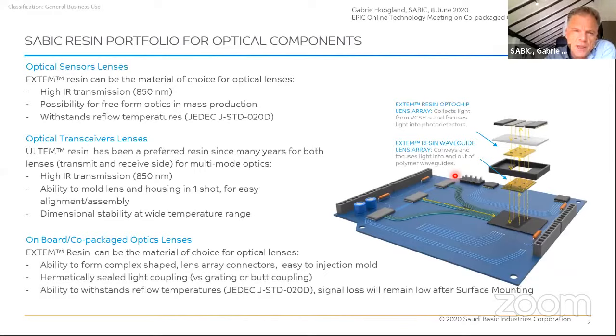molding machines, they can easily produce tens of millions of lenses in just a few months. The second example on this page is well known to you. These are the lenses used in a pluggable optical transceiver, which I guess everyone knows are mostly made from Ultem resin. And the reason why they use Ultem here, both on the TOSA and the ROSA side, is really the fact that the thermal expansion coefficient is extremely low, so it gives you good dimensional stability at a wide temperature range. Next to that, you can not only mold the lens, but you can also mold the fixture in one shot for easy alignment of the light.